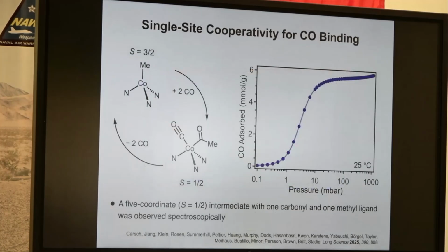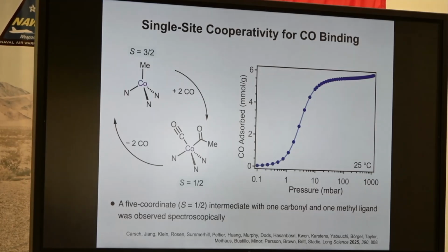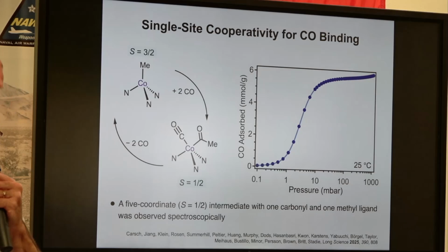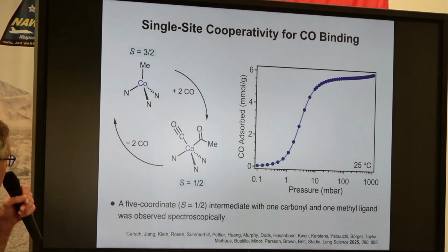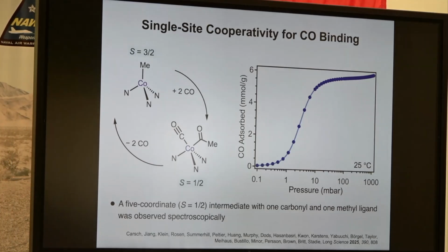And if you look at this adsorption data in a log plot, it's not a Langmuir isotherm. It has a shallow step. And that's because the first molecule of CO that binds the cobalt, it creates a 5-coordinate cobalt that's low spin. And then the second CO binds at an even stronger binding energy. And so this is now site selective or single site cooperativity for the first time in a porous material. And so the Hill exponent here is 2, as you'd expect for the reaction.